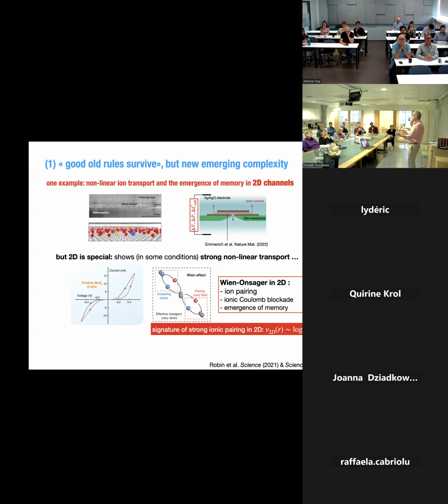And if you do that in 2 dimensions, actually, it's quite different from 3 dimensions. And you have this kind of response. So basically, at zero field, you have a pair. You start pushing the field. At some point, they break. You start to conduct. And again, the dynamics come from the separation and reformation of the pairs.